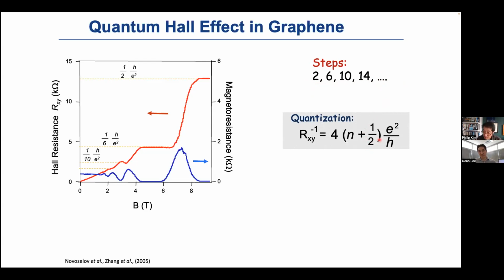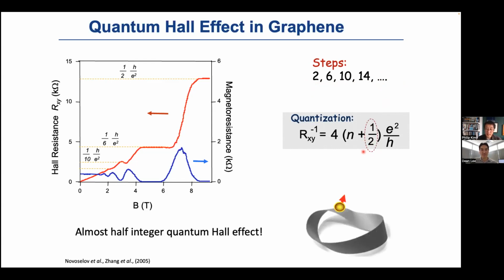And what makes the difference is basically the presence of a half integer. That's related to the fact that in graphene, the spin or the graphene electron, you have to make 2 turns to come back to its own. If you make only 1 turn, it's effectively a half turn, and that's basically the origin of this half integer. And again, this is a nice example of how the topological consideration becomes quite important to understand a physical observable. In fact, this is the interesting part, showing the topologicalness of graphene.